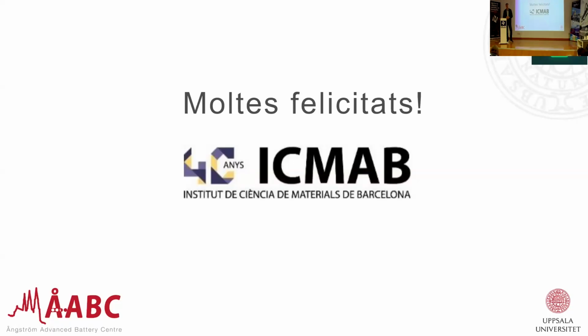Other questions or comments? Thanks so much, Patrik. I had a question about the electrolytes and their combination with calcium, because you said that there was some decomposition of the solvent during that process. So, I guess that's a massive opportunity because there are a lot of solvents. In that specific case, I think it was DME, right? Yeah. So presumably this is a deprotonation of the DME somewhere on it. Most likely. So what bank of chemical knowledge is there about the reactions of metallic calcium in this case with different organic substrates? Because lithium chemistry, for example, is very well developed. As far as I know, calcium chemistry, organo-calcium chemistry is not.